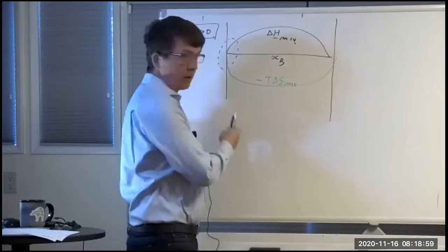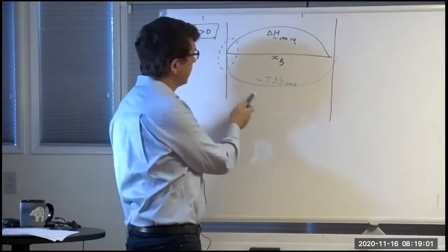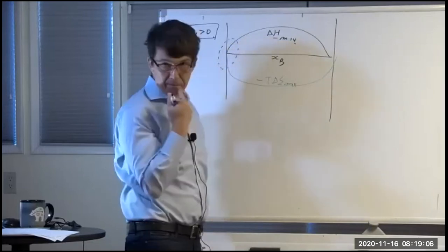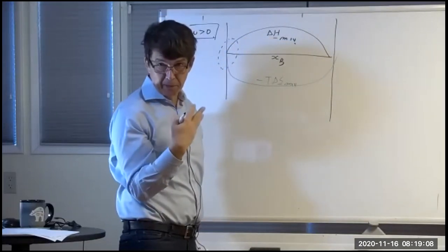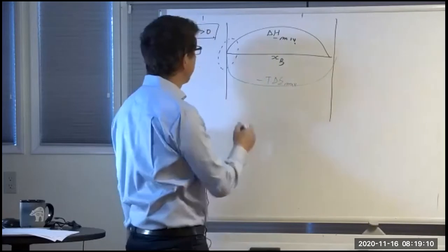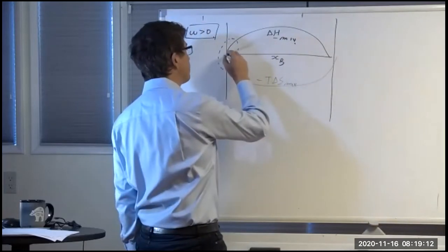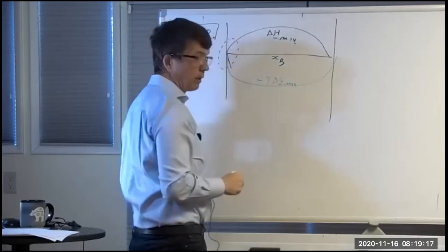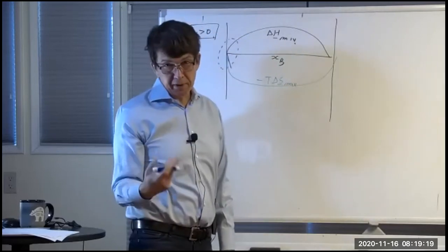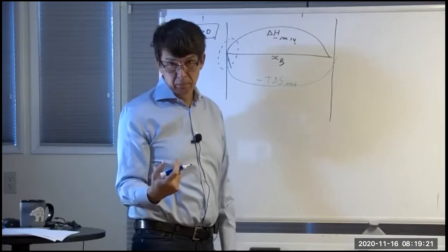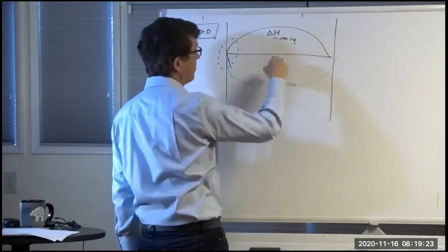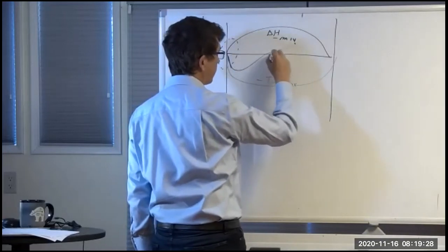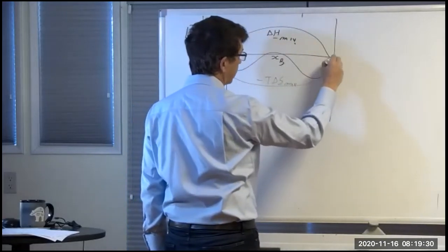So the minus T delta S term has a negative downward slope here, whereas the delta H of mixing has a finite positive slope. That means that for any T, the free energy curve starts off going downward. And this is important because when T is small, at some point I have to basically get the delta H curve back, right? So at some point this actually has to go back up, and it does something like this.